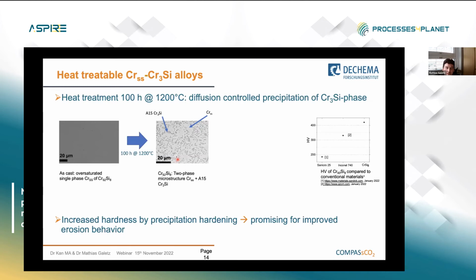And they not only increase the creep resistance, which is beyond this talk, but you can see on the right side that it strongly increases the hardness. This is the Vickers hardness at room temperature, and we compare it to two commercial alloys, the Inconel 740, which is a high nickel-based alloy, really the high end of those that can be manufactured as tubes for receiver material or heat exchanger materials. And then we have Sanicro 25, which is also a high strength iron-based alloy, the upper end that can operate up to 700 degrees C.